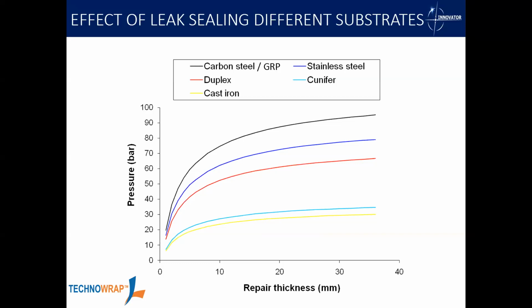So this slide is fairly similar to the previous slide. It's a slightly different set of inputs, but in this case we're changing the substrate material. You can see the top line, what we bond best to is the carbon steel or GRP. We bond pretty well to stainless steel, pretty well to duplex. But at the lower end of the scale, you've got the cupronickel and cast iron lines, which we don't bond quite as well to.